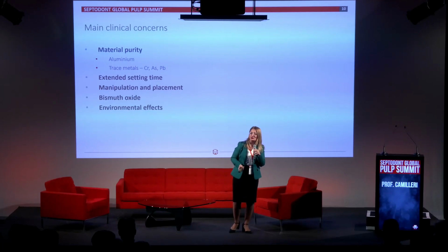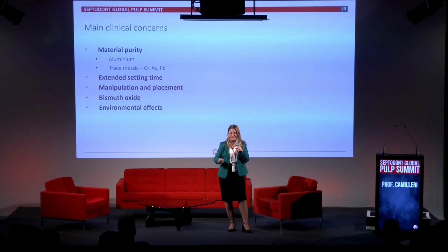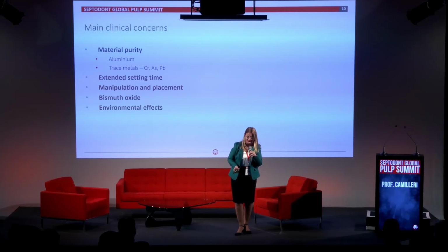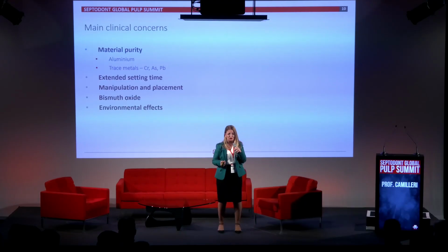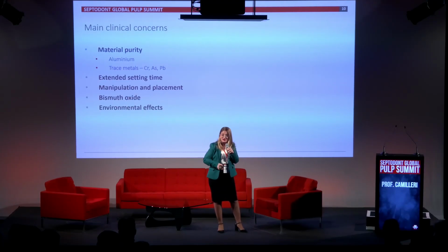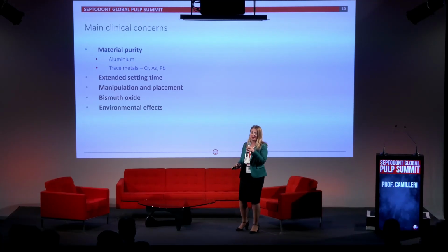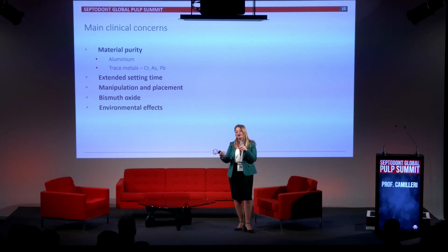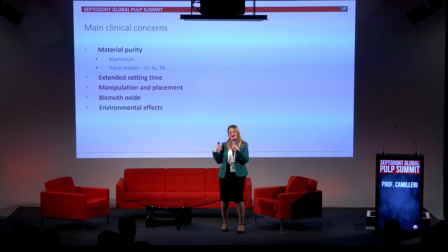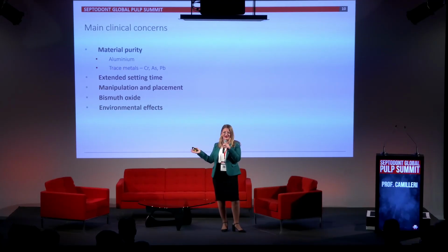The extended setting time, which I've said why, essentially, the extended setting time is because of the calcium sulfate. Manipulation and placement: it is a very sandy and very annoying material to use, although some clinicians tell you, I'll use it and I'll use it all my life. The bismuth oxide is of concern because it causes tooth discoloration, and the environmental factors, but that is us, the clinicians. Somebody suggested earlier, I think it was Angelo, it is about having a clinical protocol, which to date, with all the 20 plus years of research, nobody has suggested.